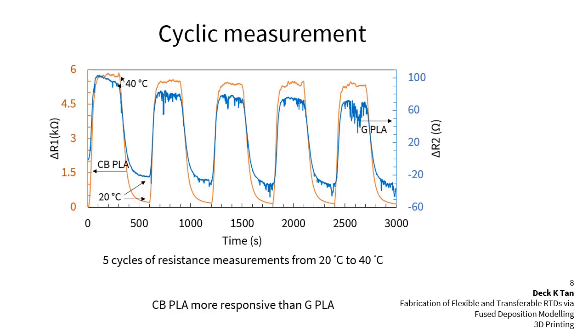Now, a temperature cyclic test was carried out on the 3D printed sensors to determine the response of the sensors to cyclic temperatures. This is because it is important for a temperature sensor to be able to produce repeatable measurements. The temperature range was set between 20 degrees Celsius and 40 degrees Celsius, and this was chosen as it is within the fluctuation of the skin temperature range. Of course, this depends on the activities of the person at that time.